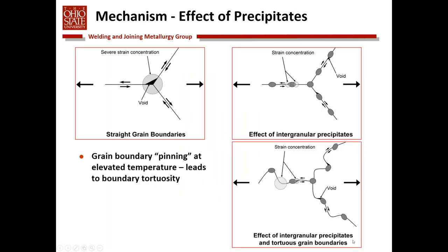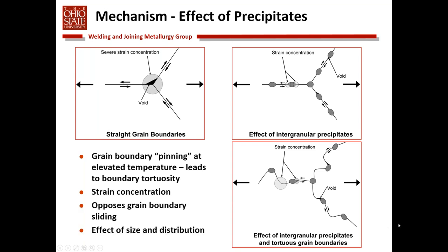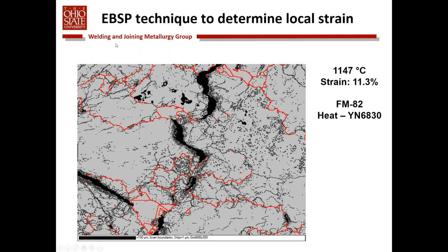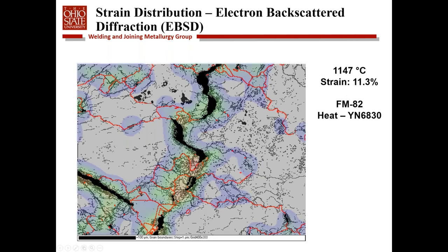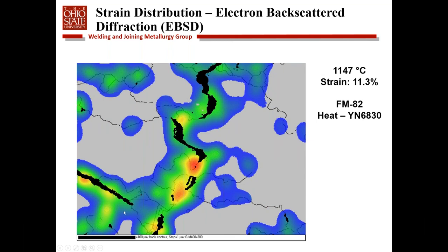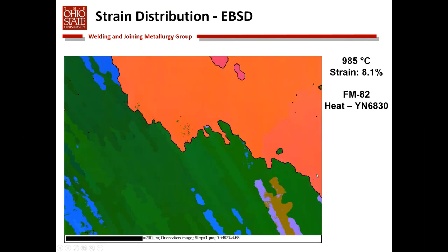I'm going to skip through the mechanism here quickly. It's basically a grain boundary sliding phenomenon, and whatever we can do to minimize the grain boundary sliding by increasing the grain boundary tortuosity can improve resistance to DDC. This is some interesting work that we've done with electron backscatter diffraction, where in the SEM, we can actually look at low angle boundary distributions in materials. This material has been strained in the Gleeble at about 11% strain. And we can develop these strain maps. And what this shows is that the strain builds up fairly significantly along grain boundaries and not elsewhere in the material. And again, this is due basically to the sliding phenomenon that occurs in this material.